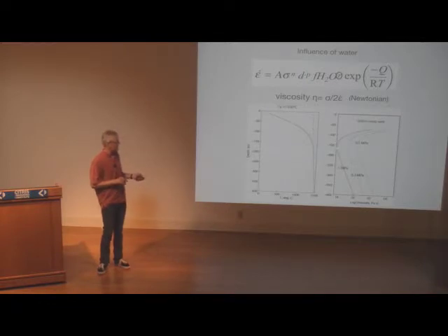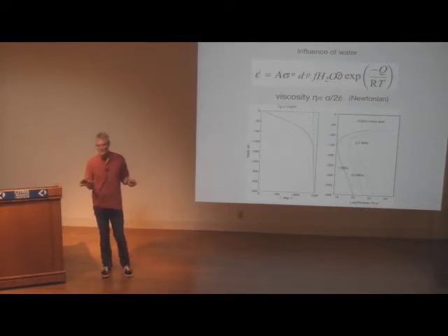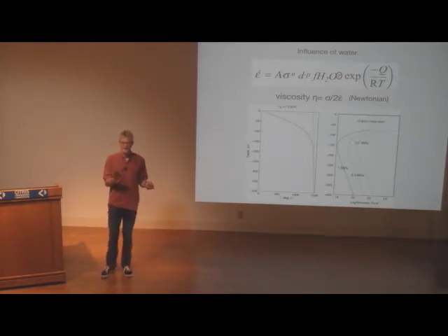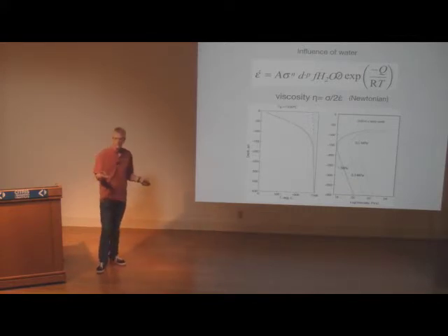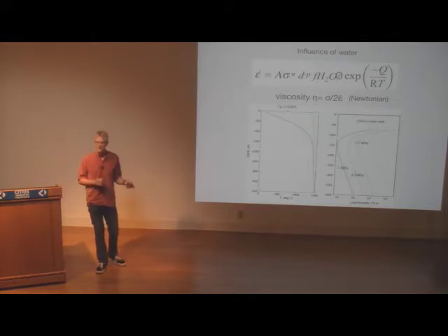The calculated viscosity, this is just for the upper mantle, varies as a function of stress. That's something important to keep in mind. That's maybe not entirely intuitive, that as you increase the stress, the viscosity actually decreases for power law creep. But going back to the influence of water,